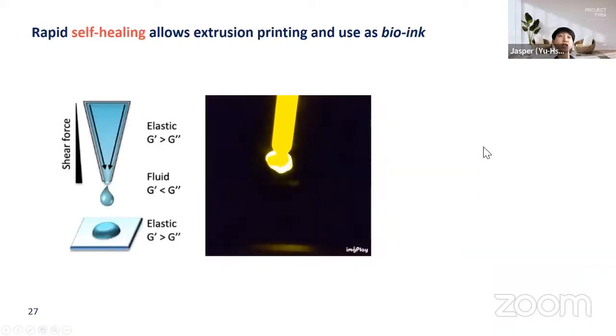This self-healing is particularly useful in extrusion printing. You can think of when the gel is squeezed through a thin nozzle, it undergoes a strong shear force. In this case, the gel is liquefied when it is extruded out, but once it's out, it will regelate and form a gel.